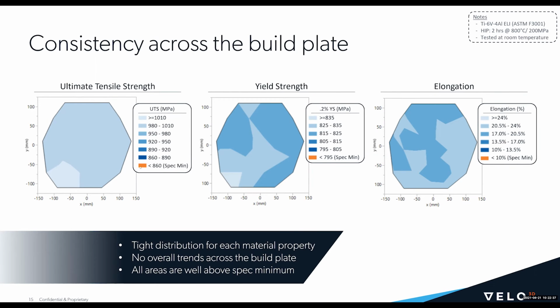When you look at these, there are really a couple of key things. First, all of the values are well above the spec minimum, in this case ASTM F3001. Additionally, you can see there's really no clear trends of variation across the build plate. And we're also getting a very nice tight distribution across the plots. So very high values, tight distribution, and you're not seeing any trends.